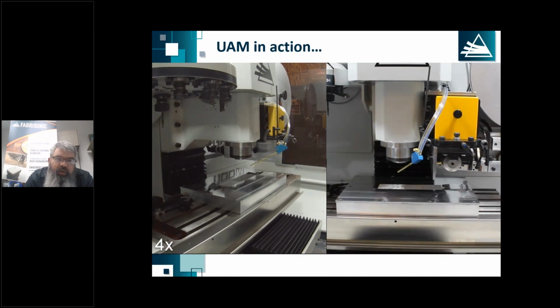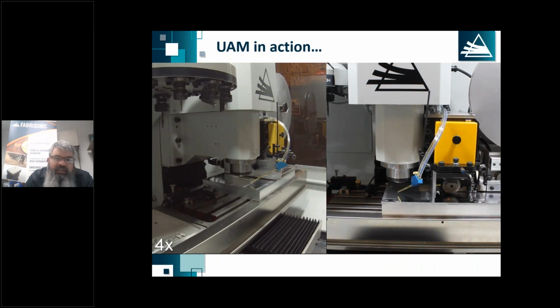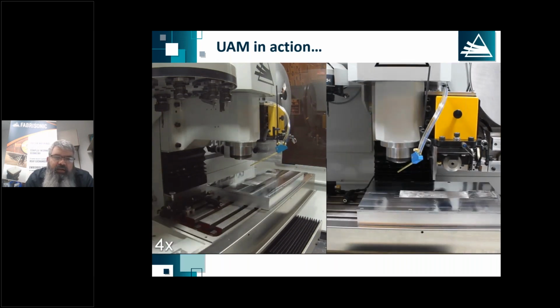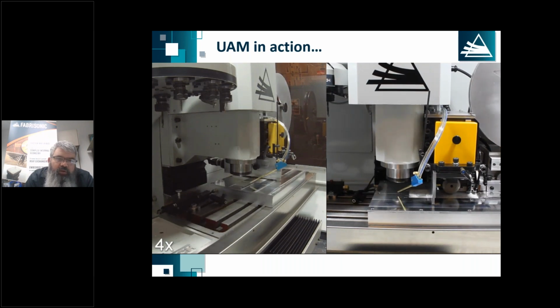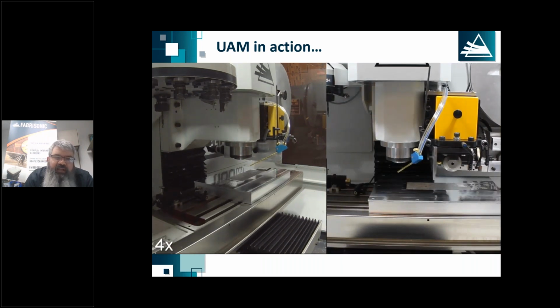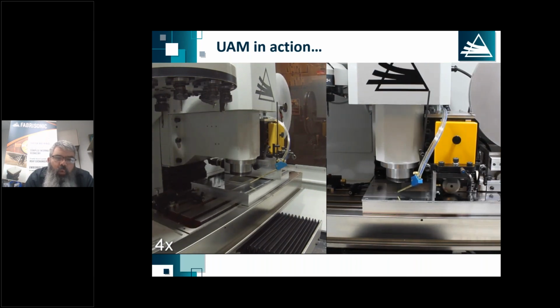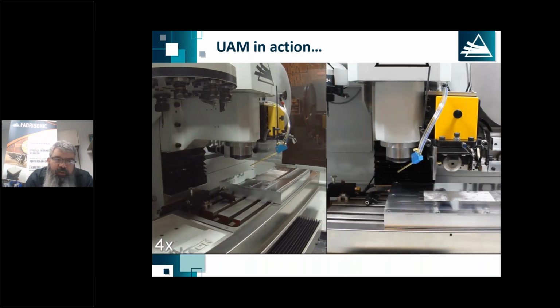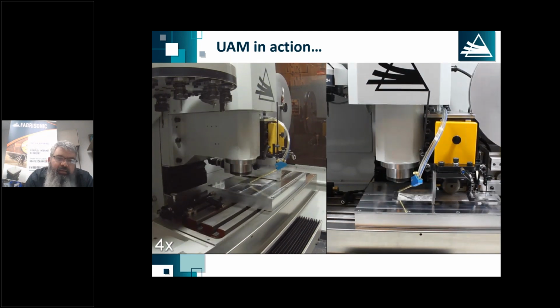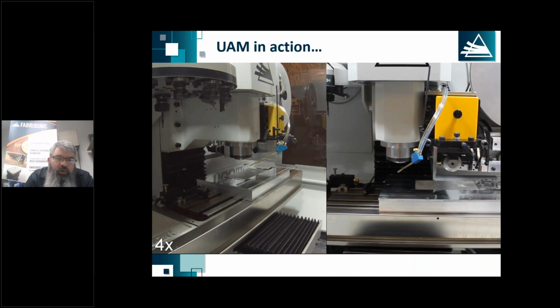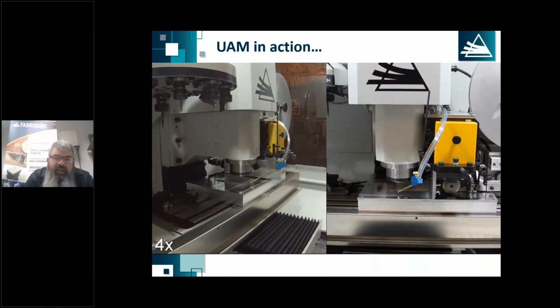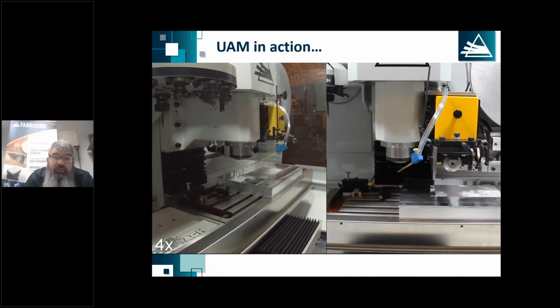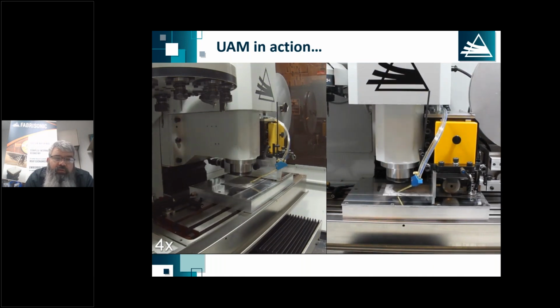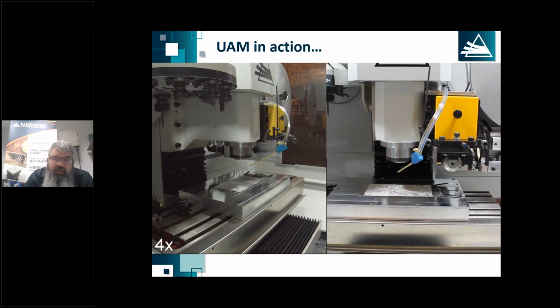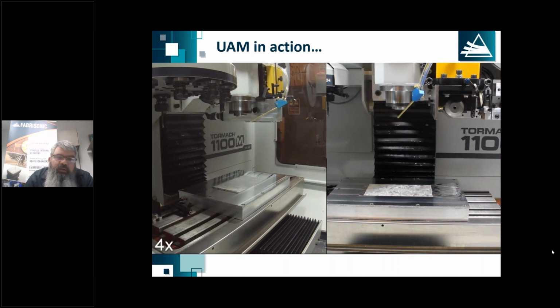Now, underneath that yellow box, you see a little cylinder rolling. That cylinder is actually the welding device, and I'll explain that in more detail later. But as that roller is rolling over a thin film of foil, again on the range of 5 to 10 thousandths of an inch thick, it's welding down that metal foil, fully dense, 100% metallurgically bonded metal. We repeat this welding over and over again. Again, we print near net shape, so we're printing kind of boxy structures that are close to the shape we want. And we derive all of our geometry specifically from the CNC milling. So from time to time, we'll stop, switch over to the mill to create the geometry as we build up layer by layer.